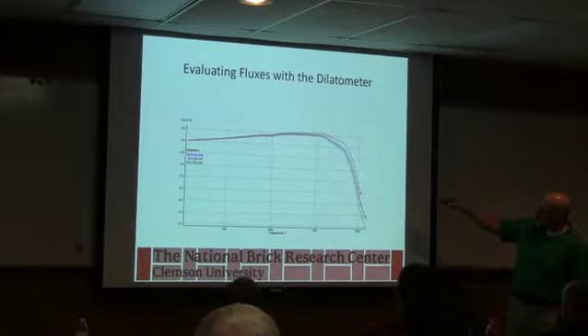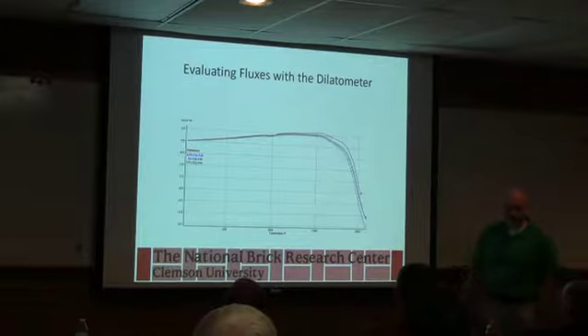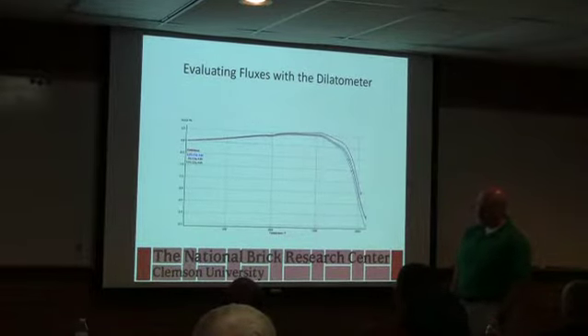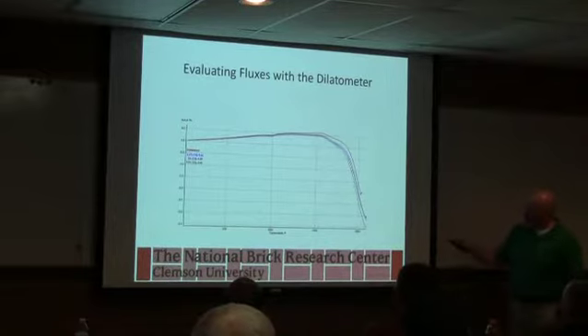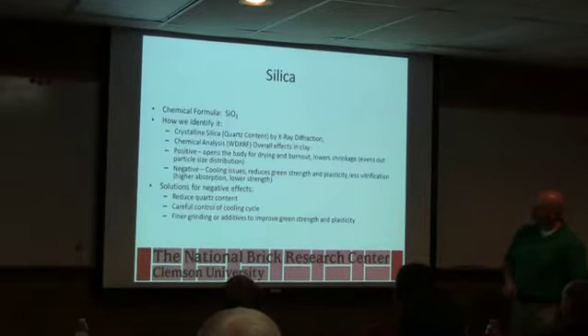So, if we're looking, say, here at 1% shrinkage as a baseline, we're close to 2,000 for the reference, and then we drop back closer to 1,900 as we increase that amount of fly ash to get the same amount of shrinkage. So it's one of the additives we'd have to look at later on for recycled material and for lowering firing temperature if we needed to.